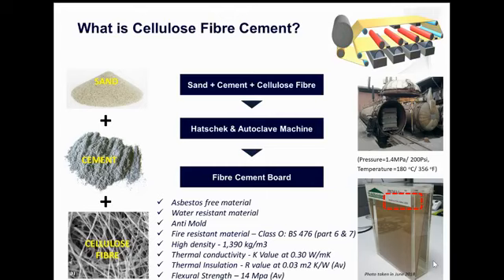Considerably high in density, Prima fiber cement is at 1,390 kg per meter cube. Not too heavy, but at the same time not too light or flimsy. On thermal performance, its K value, which represents the conductivity, is low at 0.3 watt per meter kelvin, and the R value, which represents the insulation performance, is good at 0.03 meter square kelvin per watt. This explains why fiber cement can be a good insulation material in roof sarking application.